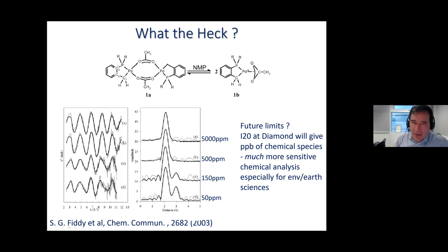So to run it in the highest possible dilution. But as you dilute this catalyst, which is in the form of two units, chemically a dimer, it has a tendency to dissociate into separate monomeric species. And it was of interest to the chemist to know that if you try to run the experiment under very dilute conditions, what was present? Was it this, or was it some combination of the two? And in performing XAFS measurements on solutions with greater and greater degrees of dilution, so 5,000 parts per million to 50 parts per million, 100 times more dilute, what the XAFS spectrum revealed on dilution after Fourier transforming was a secondary peak. And what that told them